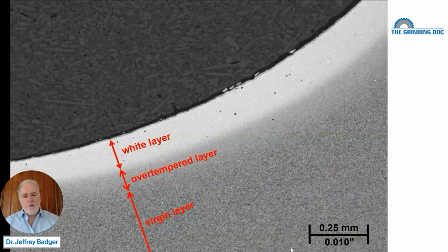So this particular workpiece, we have a white layer that's about 0.2 millimeters deep. And then below that we have an over-tempered layer that's maybe 0.15 millimeters deep. And then below that we have workpiece that has not changed. Now you'll notice you don't see any cracking in this white layer. Just because you have white layer doesn't mean you have cracking. In fact, most rehardening burn, most white layer doesn't have cracks. Things were not bad enough to cause it to crack. Things were just bad enough to cause it to get white layer.